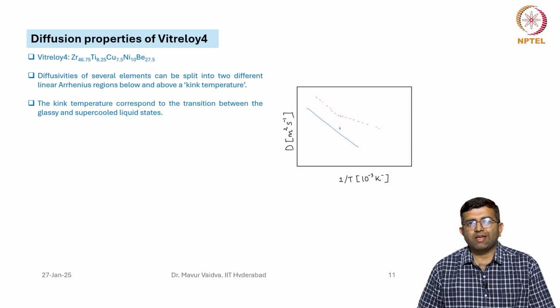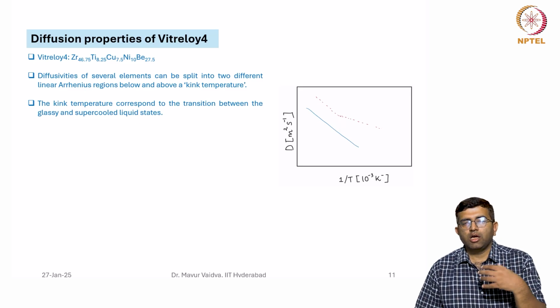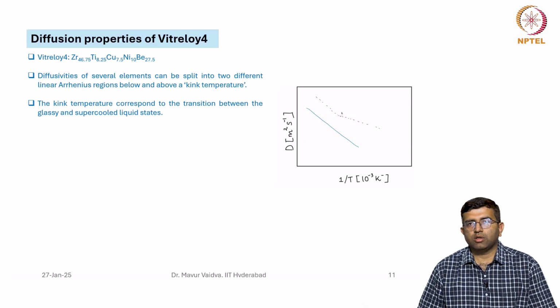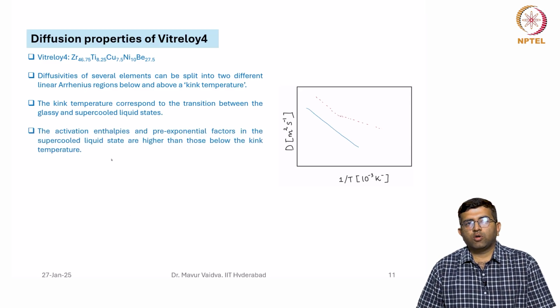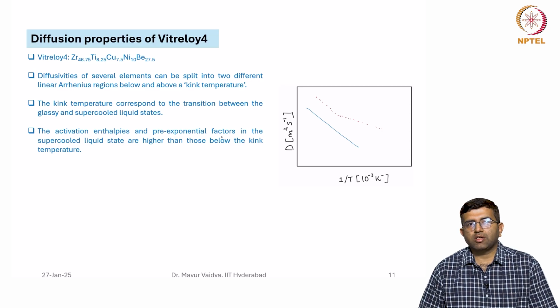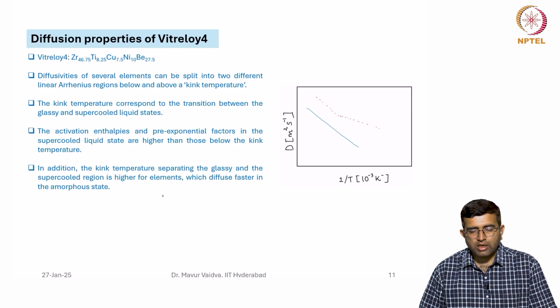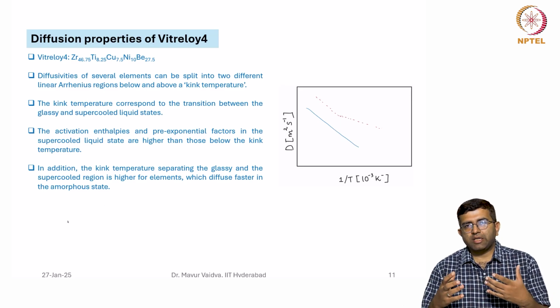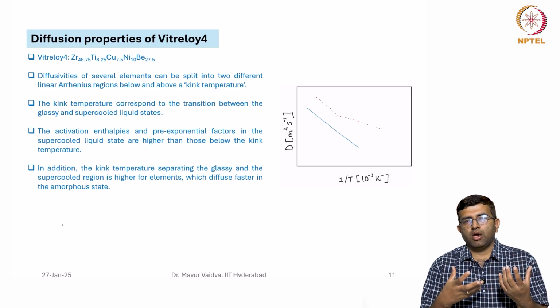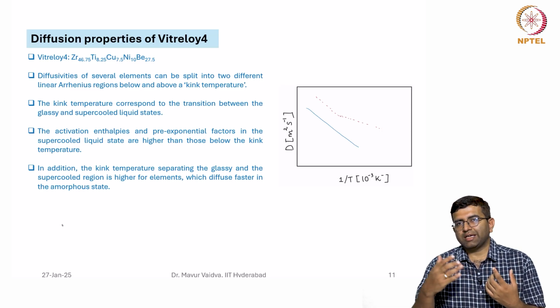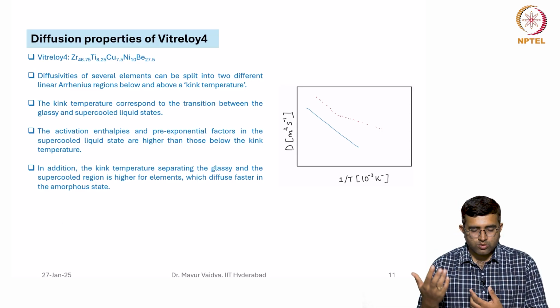It corresponds to the transition between the glassy and the supercooled liquid state. So the kink temperature refers to the transition from the glassy state to the supercooled state. The activation enthalpies and the pre-exponential factors in the supercooled liquid state are higher than those below the kink temperature. In addition, the kink temperature separating the glassy and the supercooled region is higher for elements which diffuse faster in the amorphous state. So if, for two alloys, the diffusivity of one in the glassy state is higher, its kink temperature is also higher.